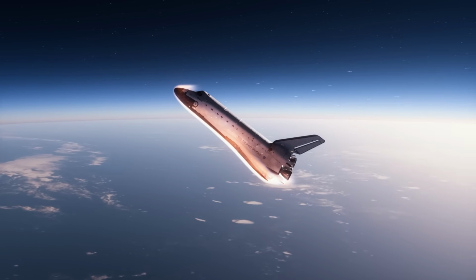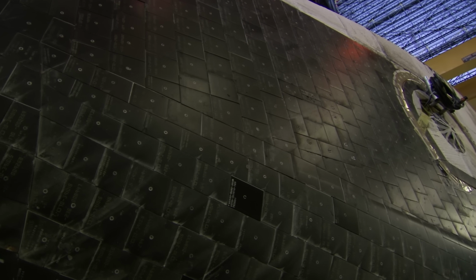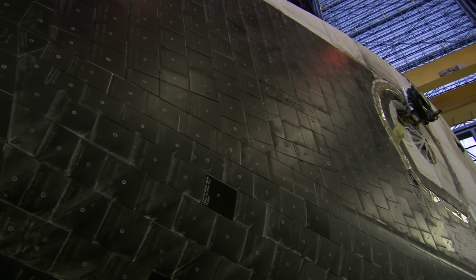The coating is where the tiles differ. The black tiles installed on the lower portion of the shuttle were covered in a black borosilicate and tetraboron silicide glass coating. This black coating helps dissipate heat before it can conduct to the vulnerable inner structure. Black for the same reason the SR-71 is black, Kirchhoff's rule of radiation. This rule tells us a good infrared heat absorber, basically anything black, is also an equally effective heat emitter. With the heat gained from hypersonic flight vastly higher than the heat gained from solar radiation, it's preferable to prioritize outward heat radiation than minimizing heat gained from solar radiation.